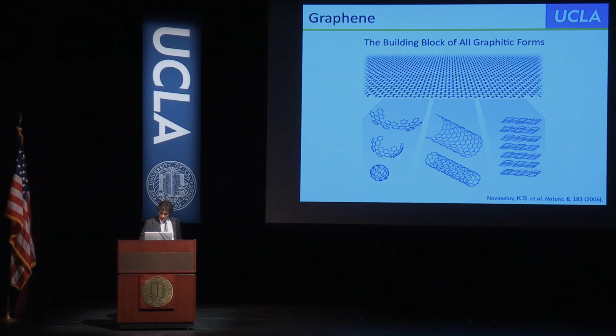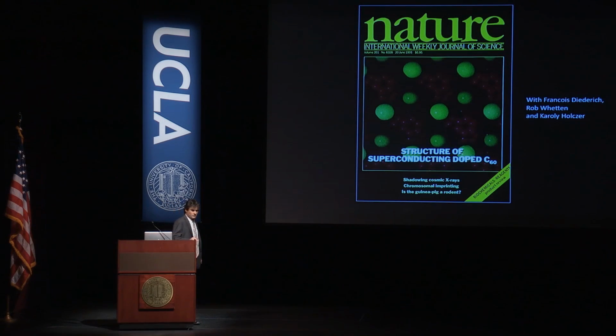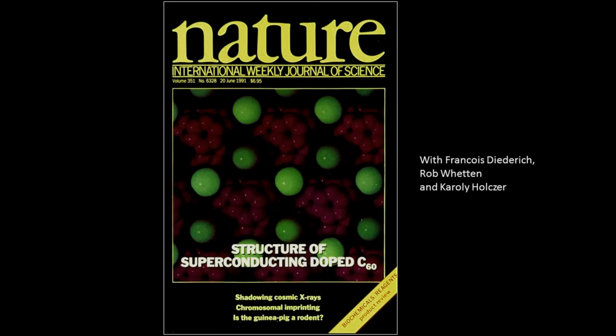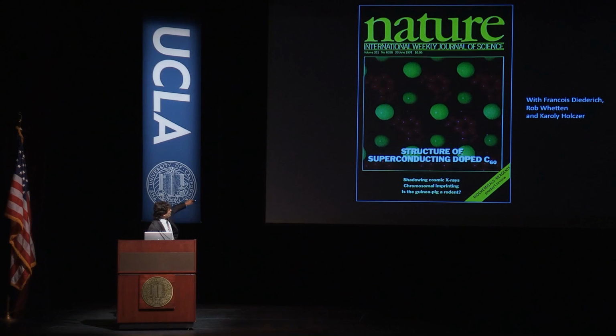Now, our work in carbon dates from the earliest time I was at UCLA. And this is work with my former colleagues, Francois Diederich and Rob Whetten. What they did is they came up with a large amount of carbon-60. And Bell Labs had just discovered conductivity and superconductivity in it, but they had a very small volume fraction. They had about 1%. We made the first pure samples and got the structure. And the structure is here, and you can see that here's carbon-60 and here's potassium. And they sit on all octahedral and tetrahedral sites.